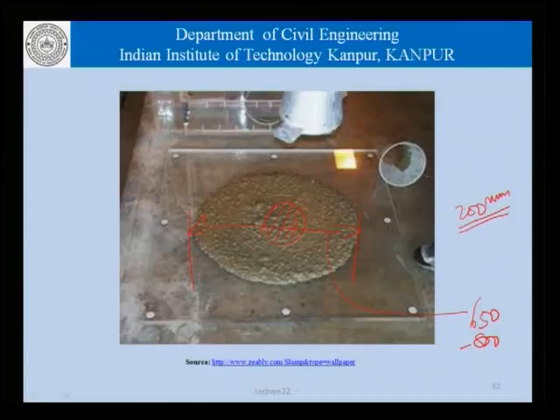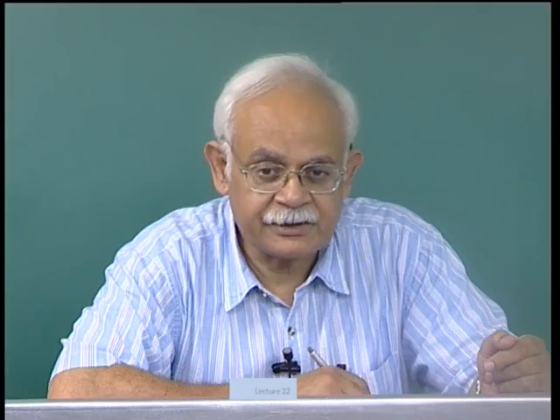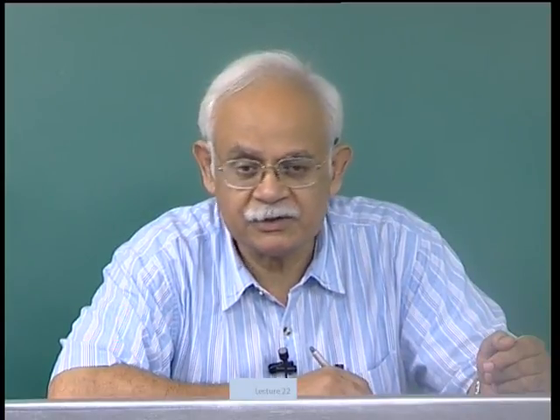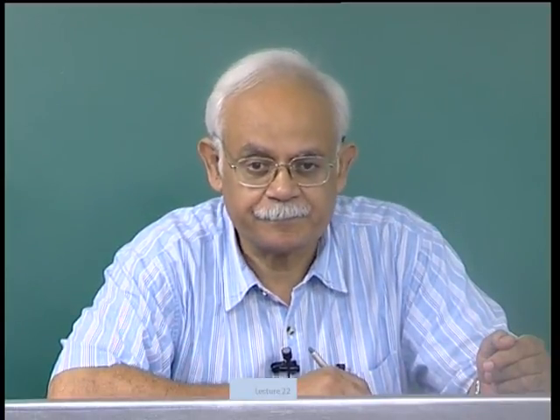When we are evaluating the concrete using the slump flow, we should also watch for aggregates having reached the edges. So, it should not happen that the concentration of aggregates in the periphery of the slump flow spread is different from the aggregate concentration in the center, and that is what is likely to happen if the concrete is segregation prone. If the concrete is segregation prone, the aggregate would not move with the mortar towards the periphery.